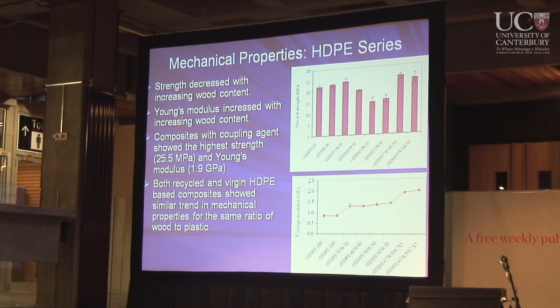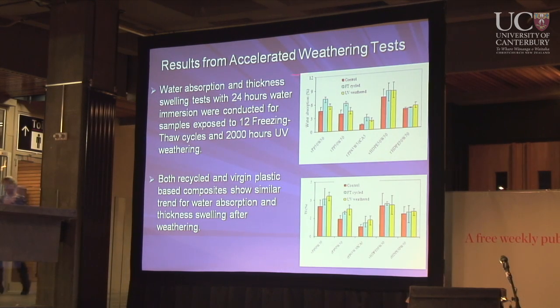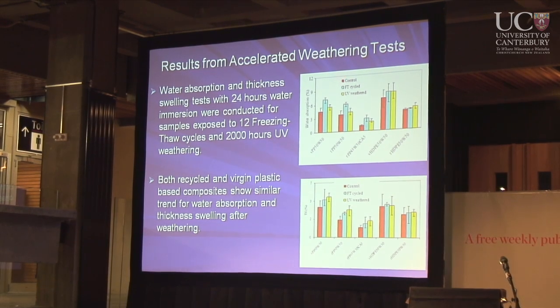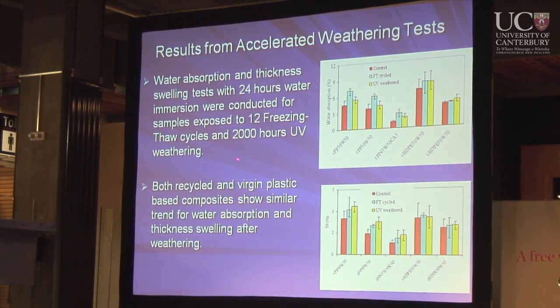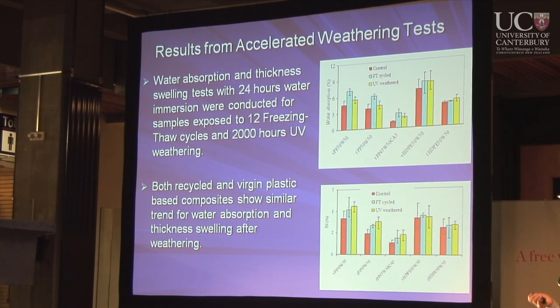How about the durability? From the accelerated weathering test, after a long time cycling of freezing and thaw, we measure the properties. These are the water absorption. After the cycling, we put the materials in the water to see whether the stability is reduced or not. If we look at the material with a little bit of coupling agent, the water absorption is very low. So it's still quite low. After quite a long time, 12 cycles, the material is still quite stable.